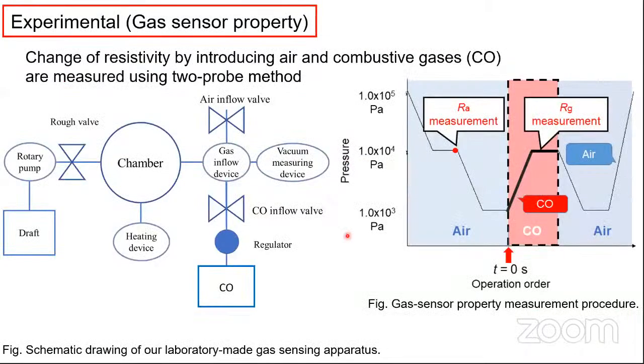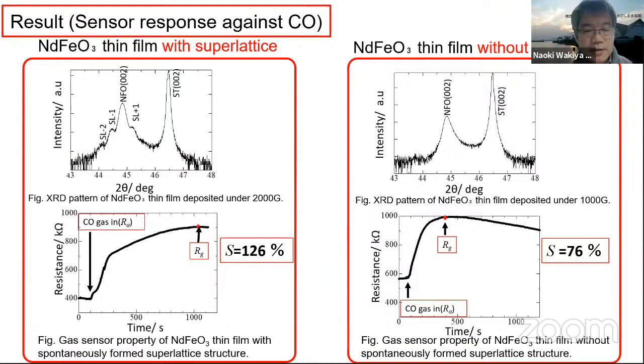And so this is sensor data. The thin film deposited without superlattice structure shows this kind of sensor response. And the neodymium ferrite thin film having spontaneously formed superlattice structures shows a higher sensor response.